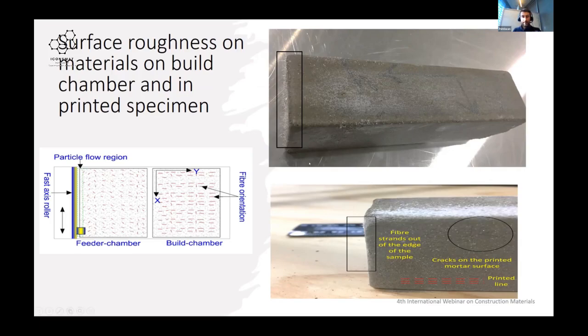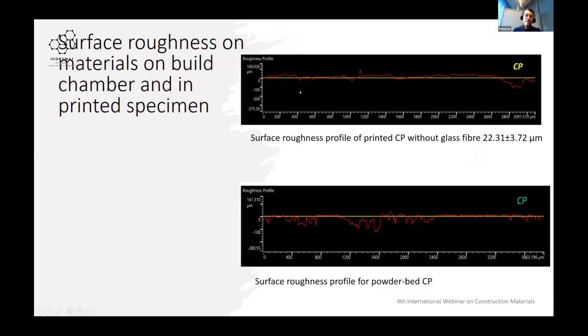This test has been done just for surface roughness. Also, we measured Ra, which is a surface roughness measurement, using a 3D laser scanner to see how it looks when checking the surface roughness profile. For the printed cementitious material without glass fiber, we saw a surface roughness of about 22.31 microns.